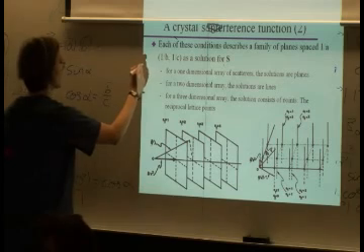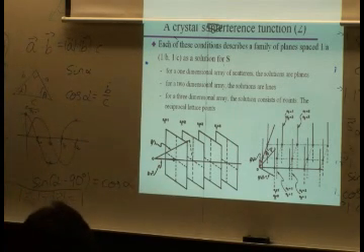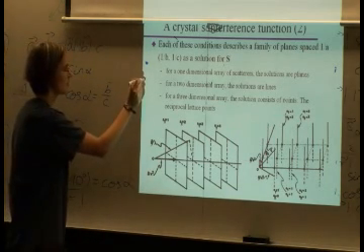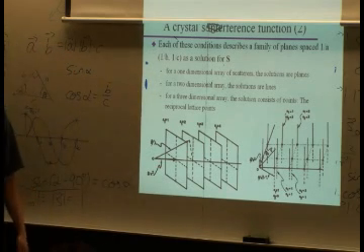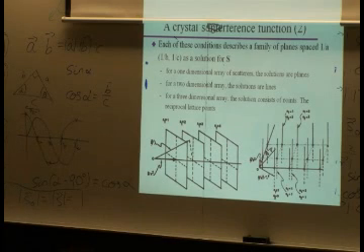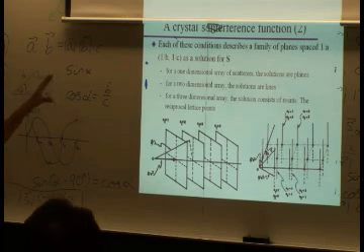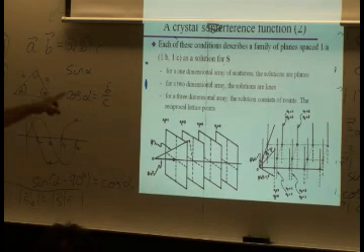So what you want to see is this, right? Nice spots. What you may sometimes see, something that looks more like that, okay? Varying lengths. Usually when something like that shows up, the crystallographer you might be working with will say, I don't like this crystal. Or they may tell you something like, your platelets are too thin. Okay? And I've seen data like that. Okay, so this happens. You won't get the infinite lines, but you might get something like that.